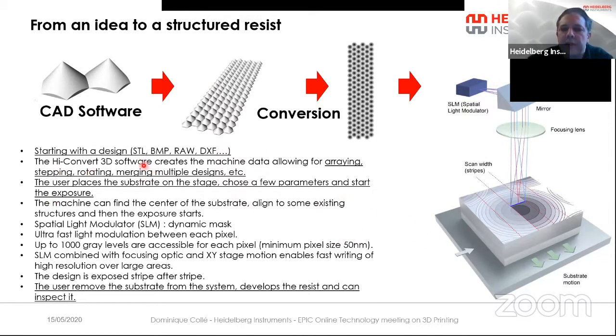And so the software creates the machine data, and it allows for arraying, stepping, rotating, and merging multiple designs. And this software can work with different types of designs, so STL, like a pure 3D structure, but also bitmap. For example, a grayscale image where the white would be the deepest structure and the black, the surface of the photoresist. And it can work also with raw file, because the typical bitmap grayscale is working with 8-bit, so 256 levels, but because our machine is using up to 1,000 gray levels, we have to use raw file in this case. It can work also with DXF, where the layer is defining the depths of the structure. And so it's pretty easy to use.